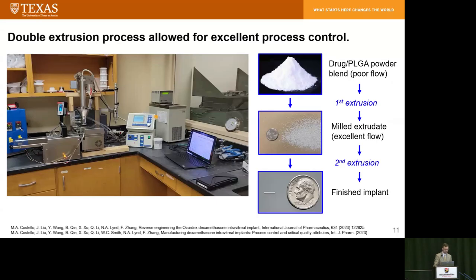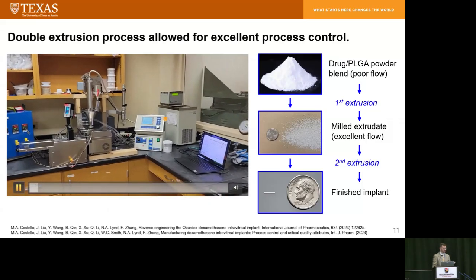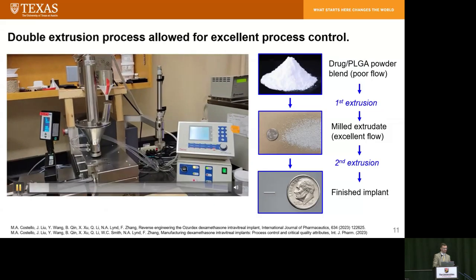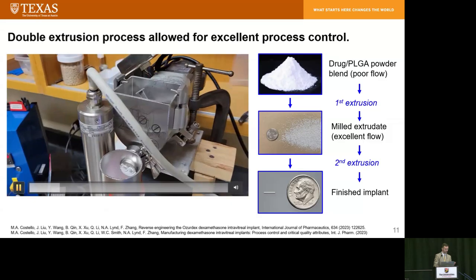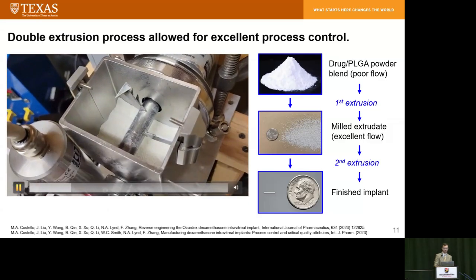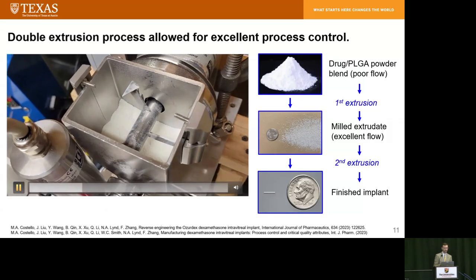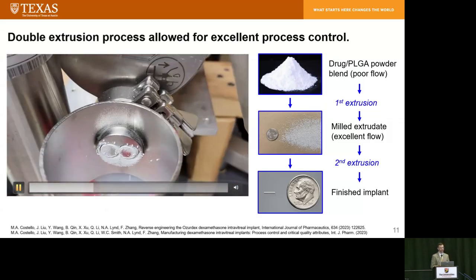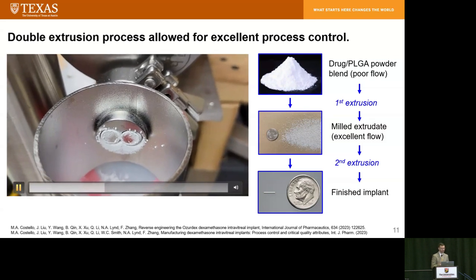So here's a video of the extrusion process. So yeah, here's the extruder, and then now we're going over to the feeders. Oh shoot, okay. So there, the feeder is in fact running. It's a feed rate of about 5 grams per hour, which seems very slow, but that's actually a perfectly appropriate feed rate. The dosage size is about 1 milligram. So a feed rate of 5 grams per hour is about 5,000 doses per hour, so that's perfectly sufficient.